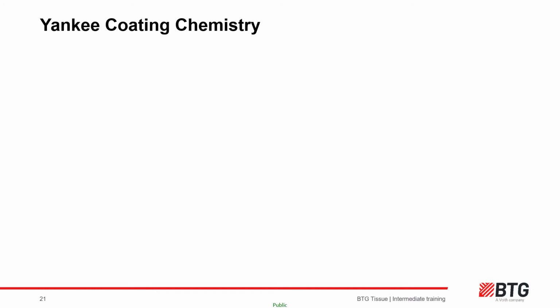The type of nozzle, spacing, distance from the Yankee, oscillation rate if any, sheet width and pressure are all taken into consideration. The water evaporates and the coating layer develops on the Yankee surface to accept the wet sheet at the nip.